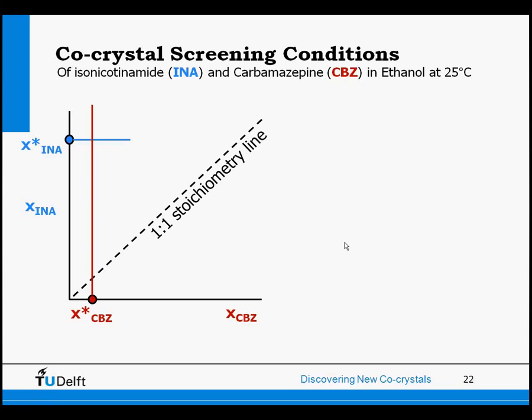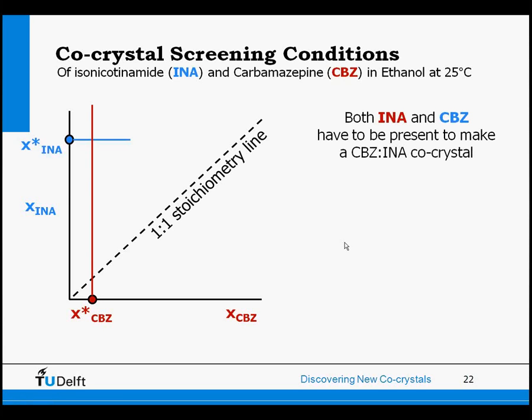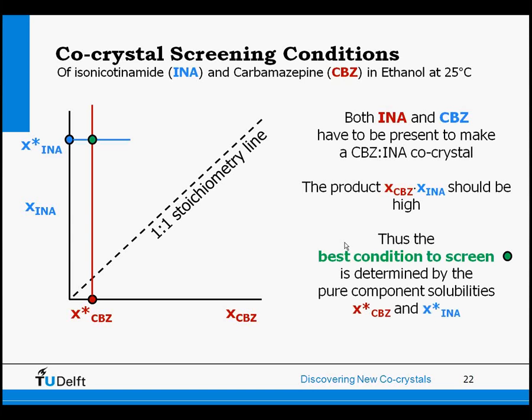So where do we want to screen now for co-crystals? So you will need both isonicotinamide and carbamazepine to be present. Well, we can say that the product of the mole fractions of carbamazepine and isonicotinamide should be as high as possible to give the highest chance for co-crystals. And then we come to the conclusion that the best condition to screen is this green point, which is determined by the pure component solubilities. So this green point is a very important point for screening for co-crystals, while it is determined by the pure component solubilities. So that is something you can measure and establish before you are going to look for co-crystals.